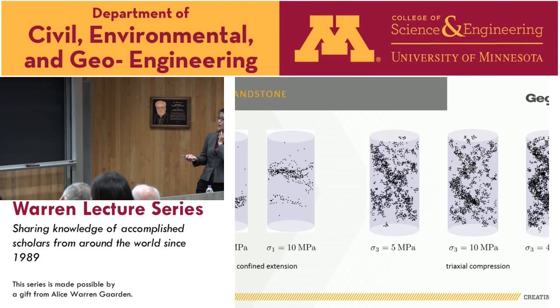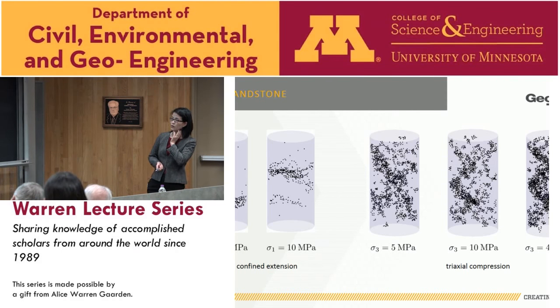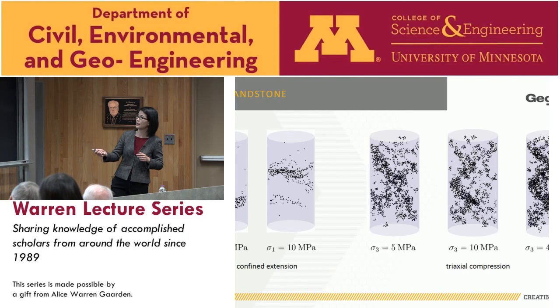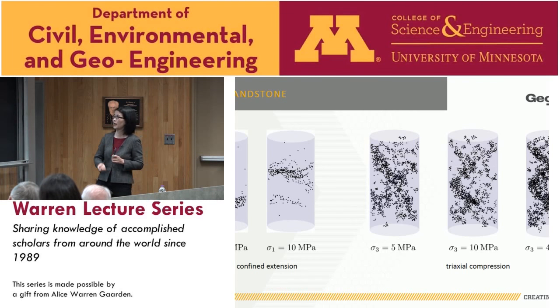And just for fun, these are the three-dimensional failure mechanisms. If the confinement is no longer small, you see the wavy shape of this crack, like potato chips. For three-dimensional, the shear band is not just a single band or a plane, it's actually a spiral kind of shape, so the trace would be helical.